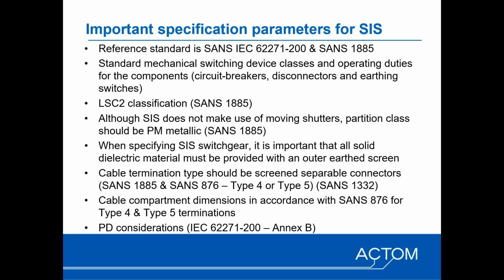So termination of cables and compliance with the requirements of SANS 876 in terms of support for the cable is essential. But with a type 5, although you need an individual inner cone bushing for each cable, that can be accommodated with the switchgear, and each cable is individually then mechanically supported when connected into the inner cone bushing. So we recommend both types, and as I say, those are covered by the SANS standards.